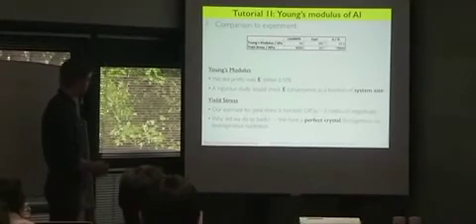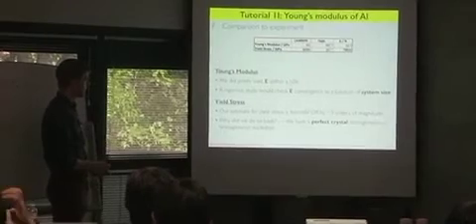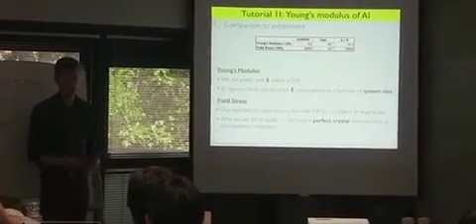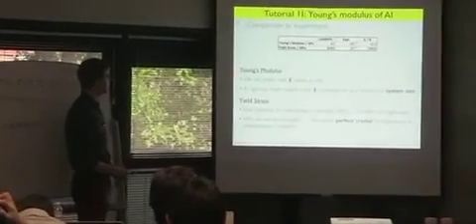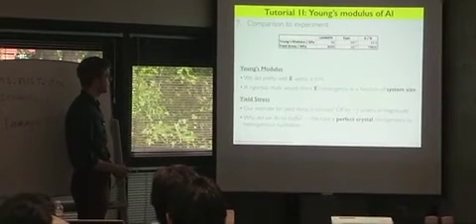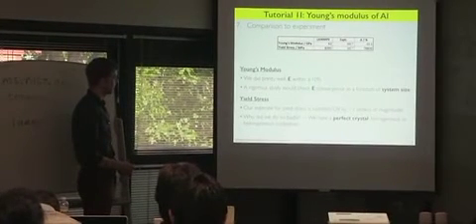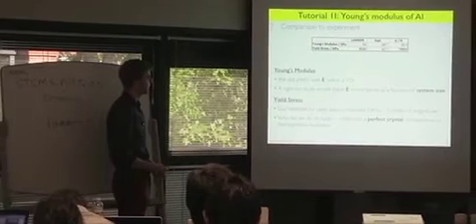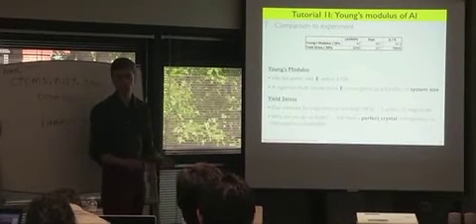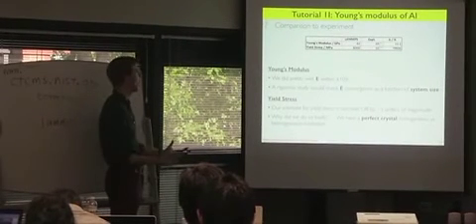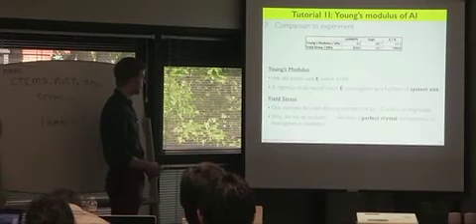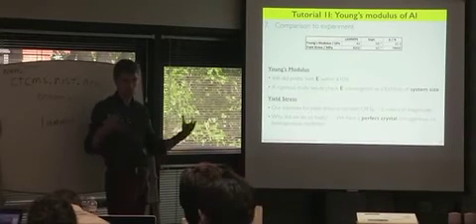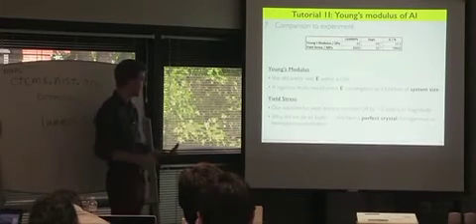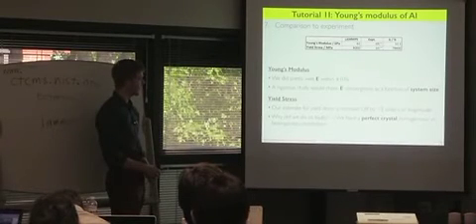So, just last slide, comparing to experiment, how did we do? Young's modulus from LAMMPS was around 62, experimentally was about 69, so pretty good, we're within 10%. Yield stress, LAMMPS said that you start to nucleate dislocations at 8,000 megapascals, 8 gigapascals. Experimentally it's more like 10 megapascals, this is horrible, so we had a horrible estimate of this, so why? Well, Young's modulus was good, within 10%. Really, we should check convergence as a function of system size, to make your system bigger and see if your answer changes. Yield stress is off by 3 orders of magnitude.